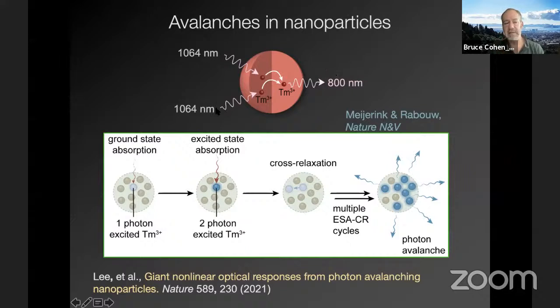And so what is photon avalanching? We are exciting these lanthanides first with one photon and then a second photon. And what this element thulium likes to do is, if there's another thulium close to it, transfer half of its energy essentially. So it's called cross relaxation. So you have a 2-photon absorbance event, and instead of emitting a photon, the kinetics of this are such that it will transfer that energy to a neighbor thulium much more quickly.